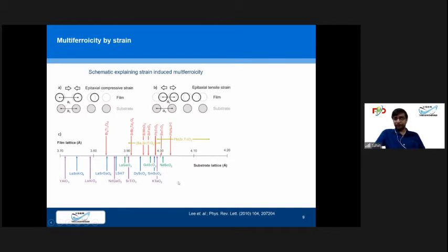But that also has a limitation, because if we continue the deposition, after a certain thickness of the material, the substrate strain does not affect much, because the material itself tries to relax. The material is deposited closer to the substrate, but as we increase the thickness, the substrate effect does not play a role. Another problem is that only in-plane strain can be created by the substrate. So we cannot